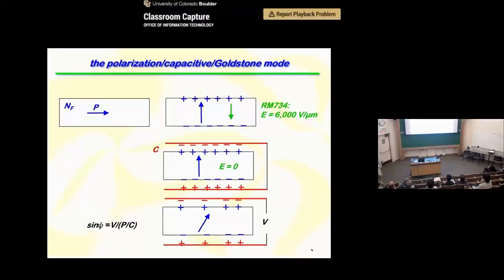Okay, so you can ameliorate this situation by adding electrodes to your slab, the red, and then shorting the electrodes. Then we have free charge running around to cancel this electric field. It'll be a complete cancellation if you can get the negative and positive charge in exactly the same plane. Then there will be no electric field anywhere, and you can rotate the polarization at will with no change in energy. Typically what happens though is you can't quite get these